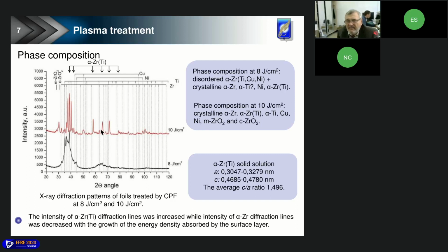A further increase of the absorbed energy up to 10 joules per square centimeter resulted in full crystallization of the surface layer. The presence of the following phases was observed: both low-temperature zirconium and titanium, the zirconium-titanium solid solution, copper, nickel, and besides that, two polymorphic modifications of zirconium oxide were found. It should be noted that the intensity of zirconium-titanium diffraction lines increased, while the intensity of zirconium diffraction lines decreased with the growth of the energy density. According to the phase composition analysis, zirconium and the zirconium-titanium solid solution, with possible addition of other alloying elements, were the main phase constituents of the analyzed layer after treatment at 10 joules per square centimeter.